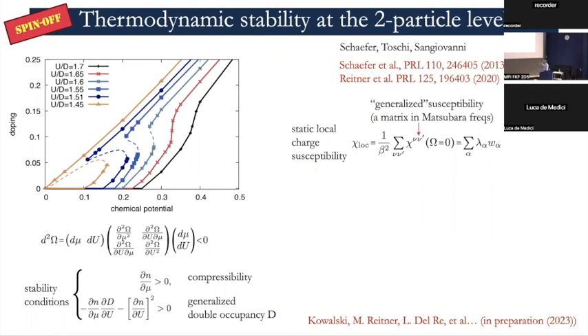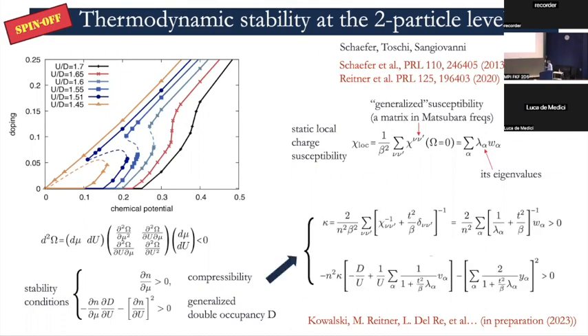And so this quantity, we call it a generalized susceptibility, depends on these two frequencies still to be summed. So you can look at it as a matrix in these Matsubara frequencies, and this matrix can be analyzed and has eigenvectors. Now, they have studied that these eigenvalues are telling you something about the system, among which we have worked out the dependence of the uniform, so q equals 0, static charge susceptibility, which depends on this quantity, and you can show how it depends on the values of these eigenvalues. And this is the second condition of stability, also expressed in terms of these eigenvalues.